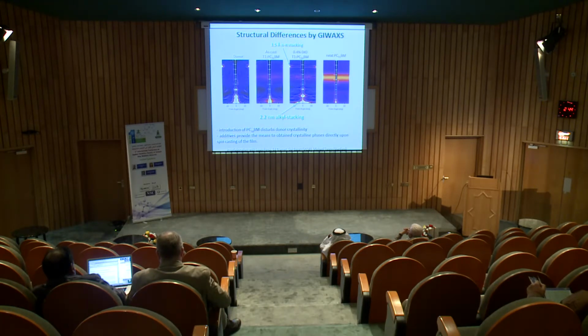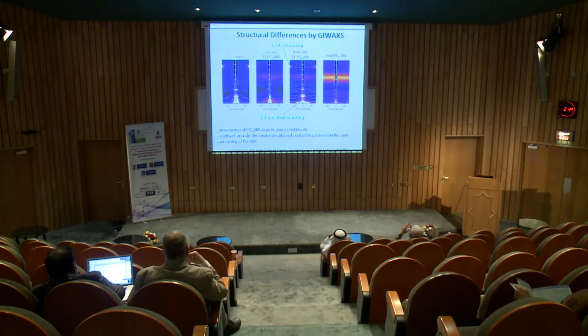And now if you look at the film prepared with 0.4% DIO in the blend, suddenly you can see the strong diffraction peaks reappear. The peak on the top corresponds to pi-pi stacking, and the one on the bottom corresponds to alkyl chain stacking. So what does it mean? The data tell us that when we blend the film and process with 0.4% DIO, we improve crystallinity and order in the device. Because of that, you can see better photocurrent and also better device performance.